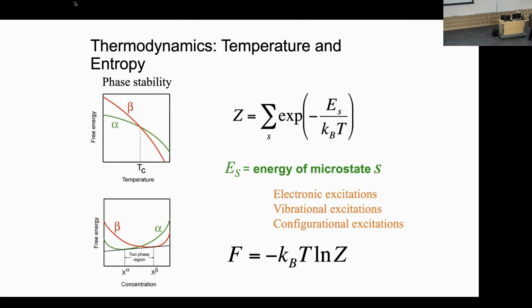The key equation there in any statistical mechanics book is the partition function, which is essentially a sum of the exponent of minus the energy of all kinds of excitations that happen in a crystal, divided by kT. If you are able to evaluate this partition function, then you can plug it into this very simple formula, and you get your free energy. So conceptually, at least formally, it's very simple. What we mean by these excitations are, first, electronic excitations. If you have a crystal, you've got electrons in it. If it's, let's say, a semiconductor, an electron can go from the valence band to the conduction band. That's a type of excitation.